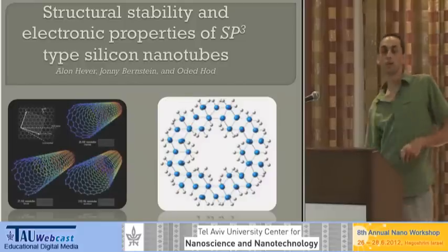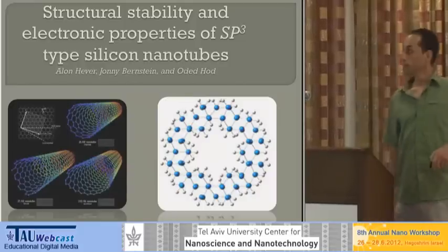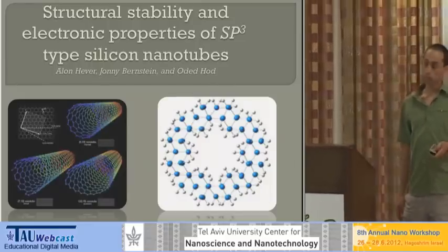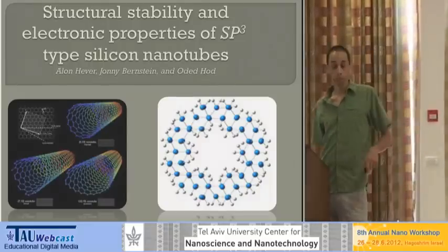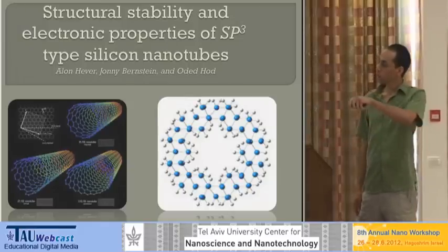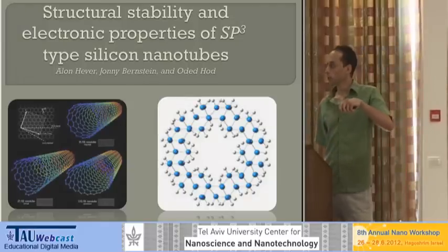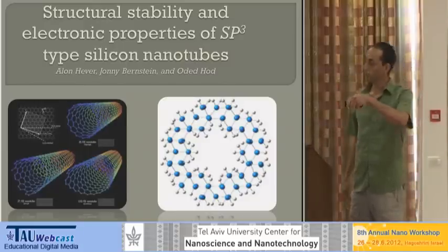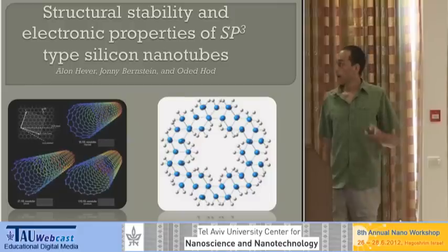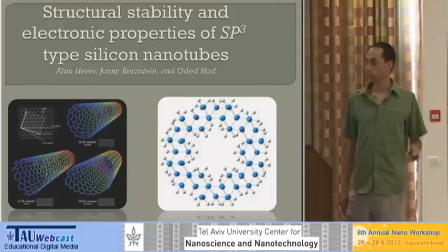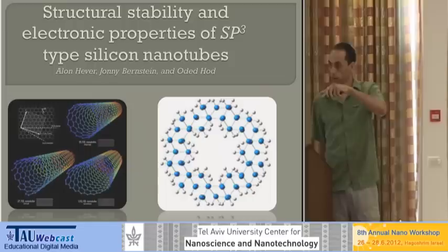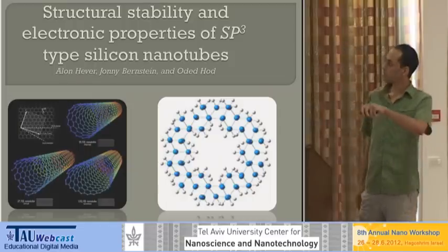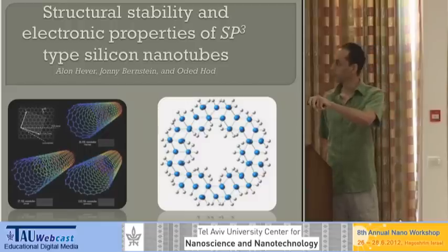Good evening. My name is Alon Hever from the group of Obed Hod. Our work deals with silicon nanotubes, their electronic properties and stability properties. Usually, when people think about nanotubes, they think about carbon nanotubes that can be imagined like a rolled graphene sheet, as you can see over here. Silicon atoms prefer sp3 hybridization, so they would look more like this one. The wall will have a thickness of a few atoms, and there will be a passivating atom, in this case, hydrogen.